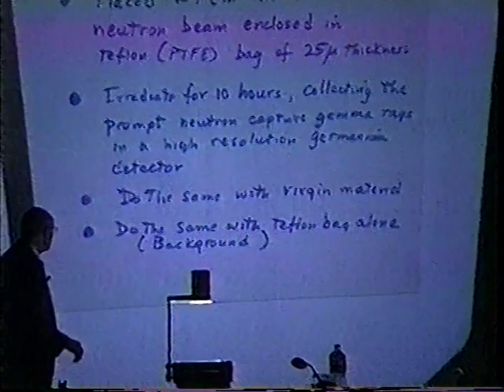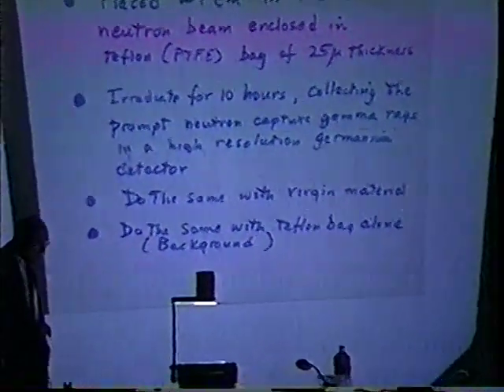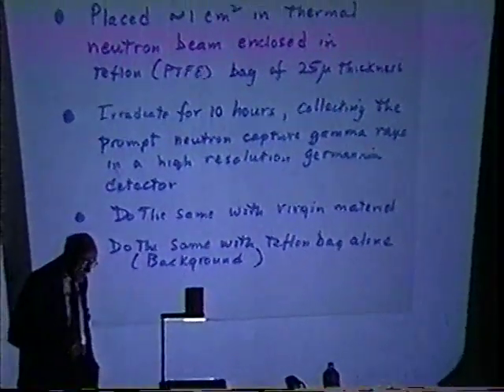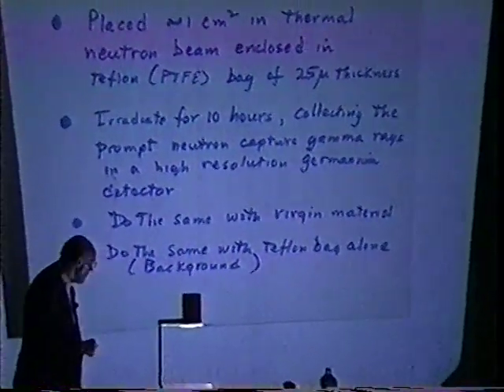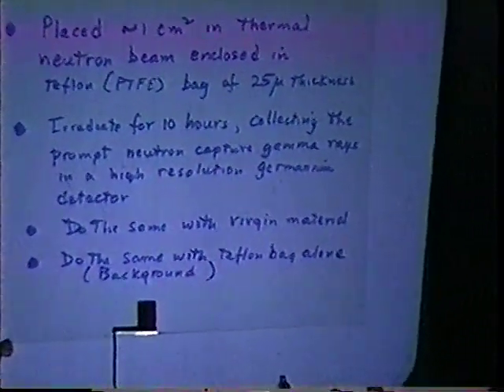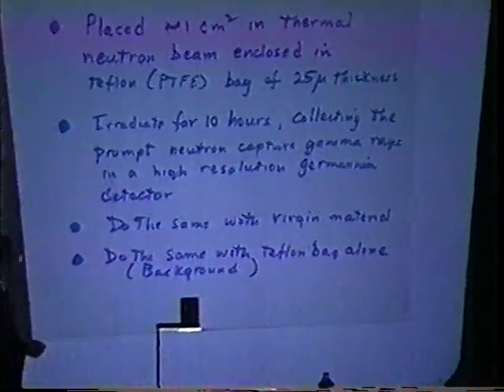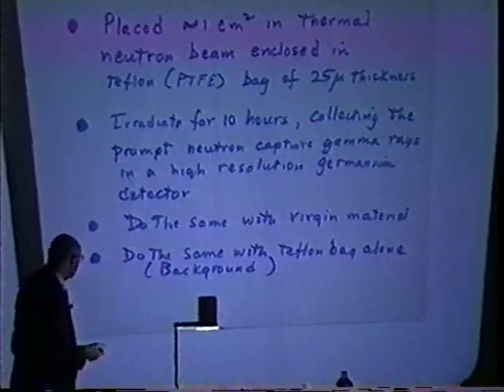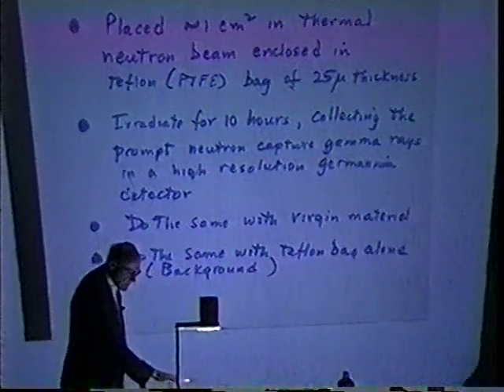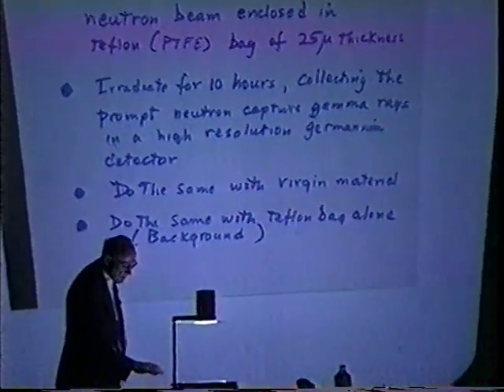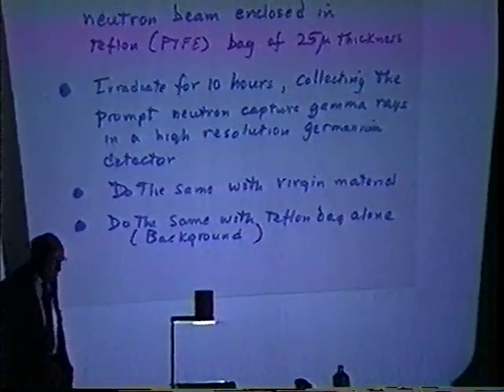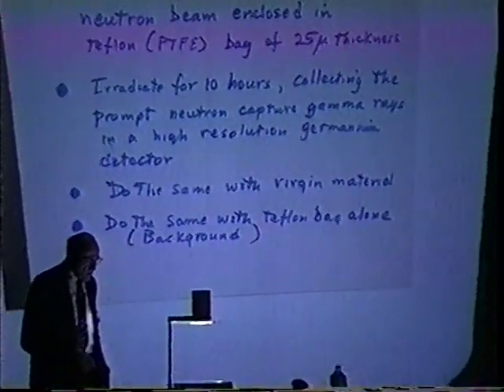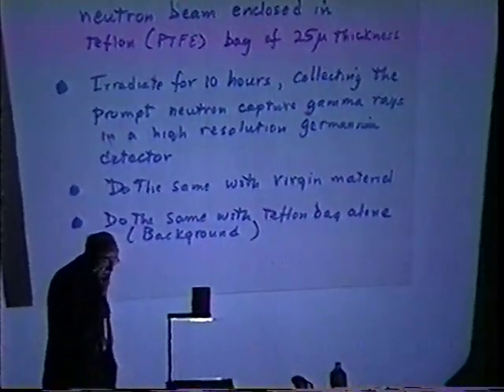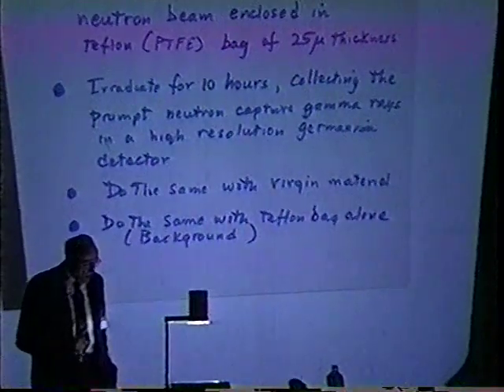to measure the neutrons that are captured by all the stable isotopes that actually capture neutrons in that sample. Now, we irradiated for 10 hours in the beam, collecting the prompt neutron capture gamma rays with a high-resolution germanium detector. And we did the same with another 10-hour run with the virgin material. And finally, with neither, with just the Teflon bag that we had the samples in, we did it for the background.